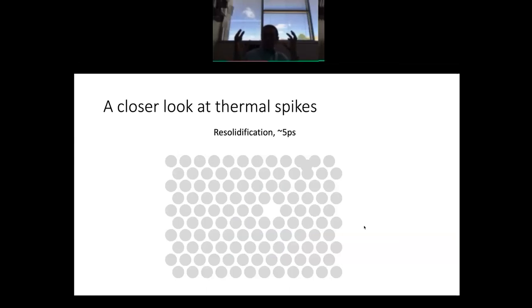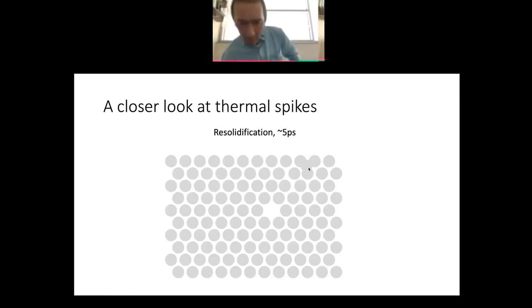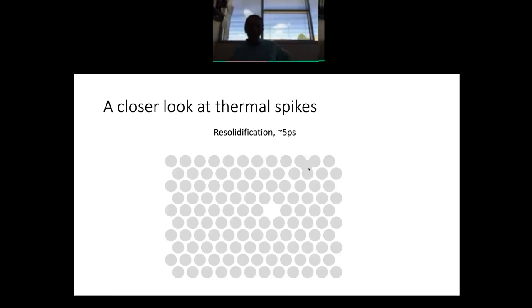So once this liquid core resolidifies, it's going to lose energy through conduction very quickly to the surroundings. So it's going to resolidify quite quickly within a few picoseconds. All the vacancy interstitial pairs that were not far enough separated from each other recombine, and the only ones that are left over are the ones that were sufficiently separated from each other, and in most cases, they're just the ones from these replacement collision sequences. So in the end, people have studied how many of the vacancy interstitial pairs survive this process, and it's really a very small number, on the order of a few percent, maybe even 1% of the vacancy interstitial pairs survive. Okay, so that's what we know about thermal spikes.